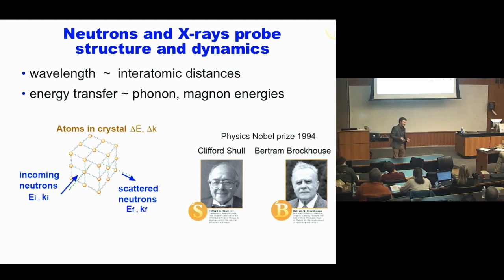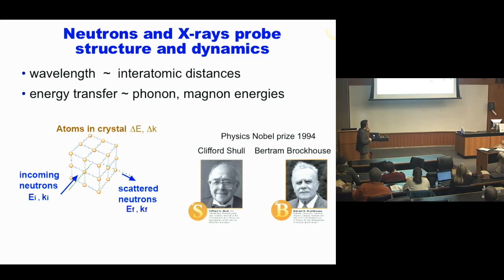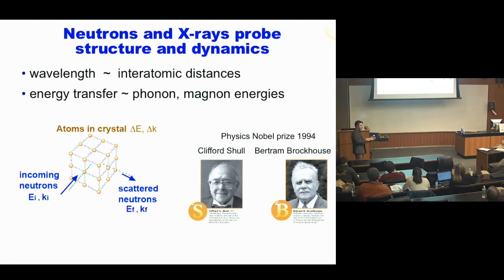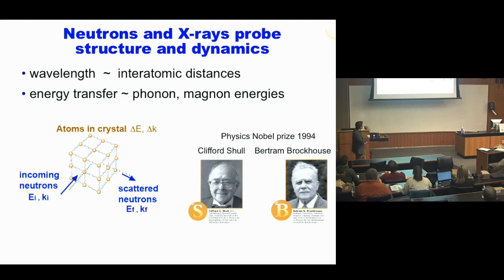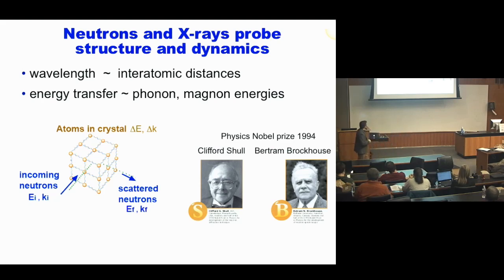Let me tell you about how we can do measurements of phonons in materials using neutrons or x-rays. Our group often goes on field trips to various sources across the country. Conceptually, the experiment is fairly simple: we need a beam of either neutrons or x-rays with wavelengths comparable to the interatomic distances in samples - on the order of angstroms - and we need to detect energy transfers between these probing particles and phonons, which are on the scale of terahertz, equivalent to milli-electron volts. We collect particles scattered at different angles and with different final energies, recording both the scattering angle and the energy transfer.